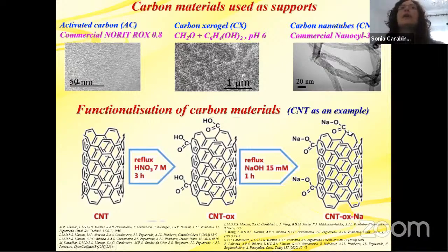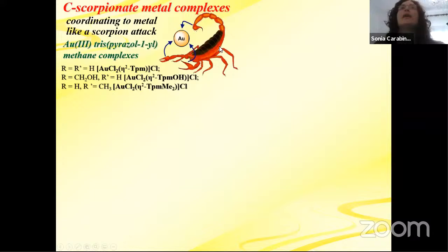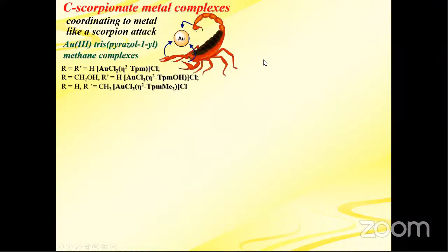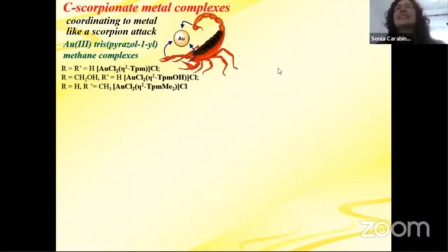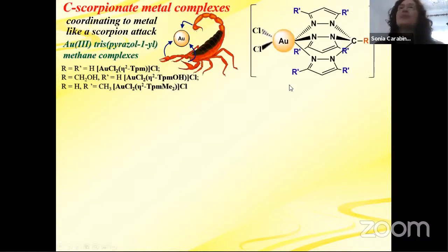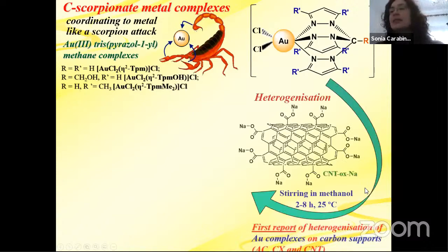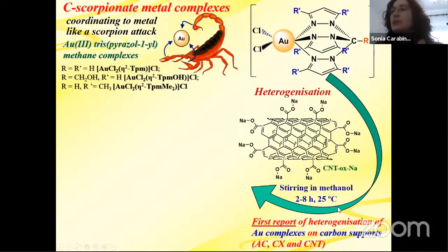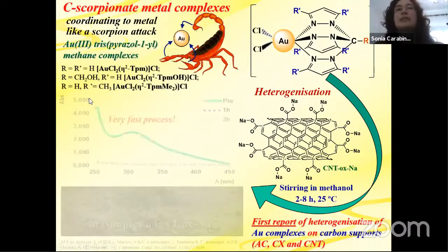And so we anchored scorpionate metal complexes on the carbon supports. They are called scorpionates because they coordinate to the metal like a scorpion attack. This is the formula of the gold complexes. They are heterogenized by stirring in methanol from 2 to 8 hours at room temperature. It's enough. And it's a very fast process because here you see before and after 1 hour, the complex has already disappeared from solution. It's already anchored on the carbon support.